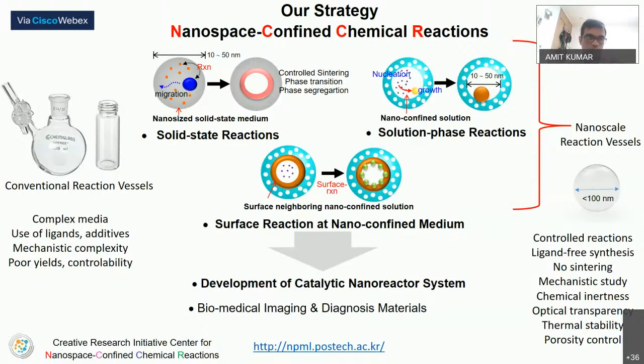Usually the synthesis of nanoparticles is done in glass vessels. Everybody in the laboratory uses vials or flasks made of glass, which is basically silica. There is a reason for this: silica is very inert to common chemicals, and it is optically transparent. So we developed a new idea to use silica nanoparticles as a nano-sized medium, and we fill these silica nanoparticles, which are less than 100 nanometers, with metal.